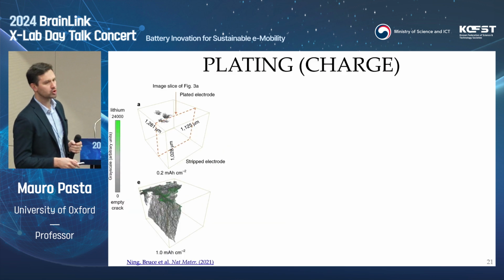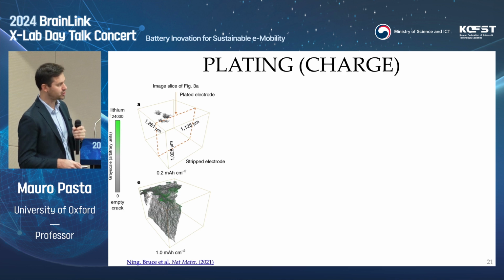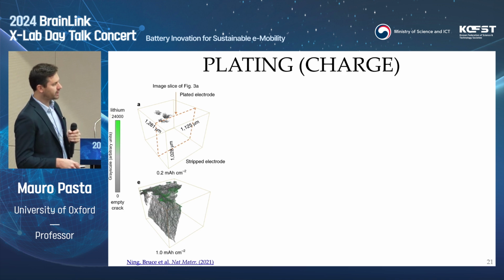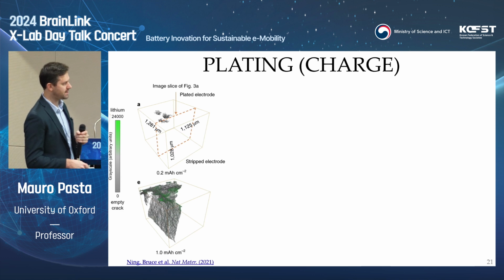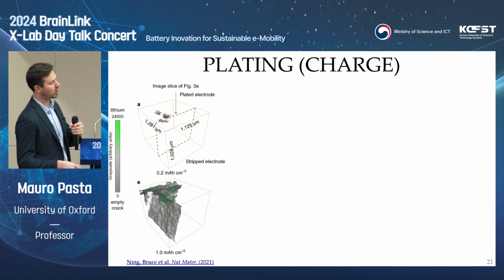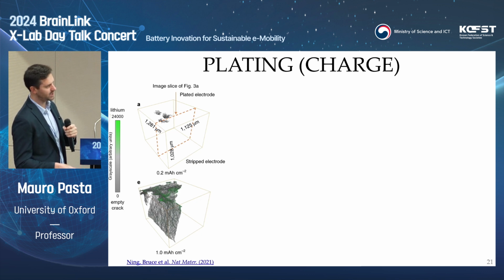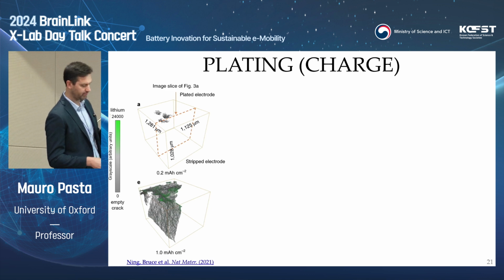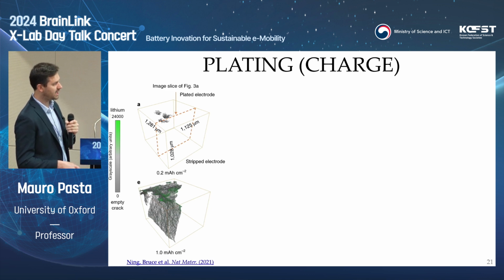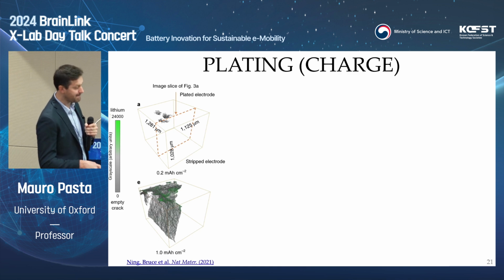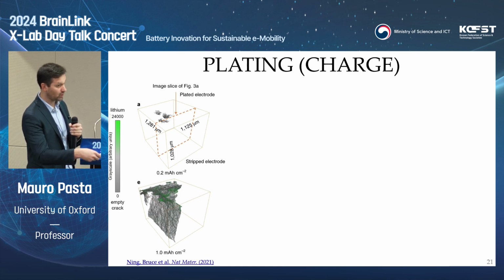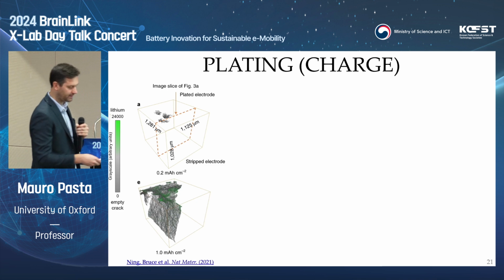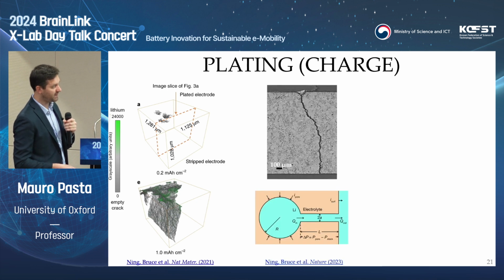Now, a few words on what is actually happening during plating or charge. There was a bit of a debate for a few years on what was actually happening there: if the filaments that I mentioned earlier were caused by lithium itself trying to plate within your solid electrolyte, or a mechanical degradation. I think there's quite a bit of agreement right now in the community, in particular in the sulfide system, that the first thing that actually happens is mechanical degradation, which leads to the formation of cracks that are then backfilled by your lithium. So mechanical degradation comes first, and then your lithium metal basically penetrates through during plating. And I think we have quite a bit of evidence of that.